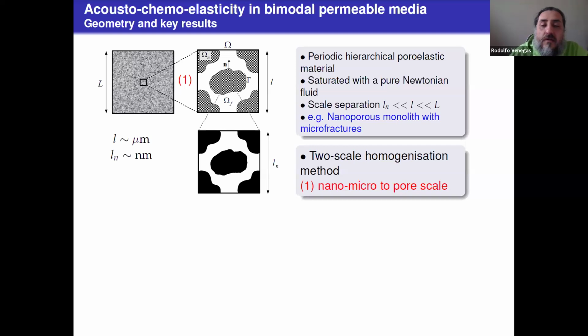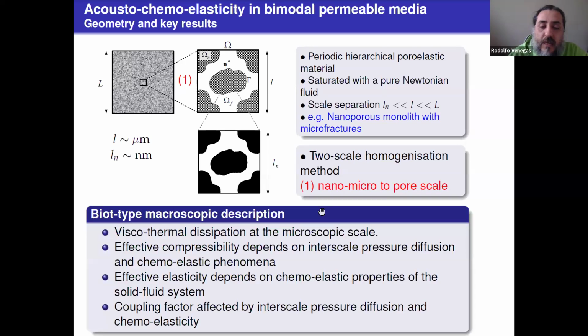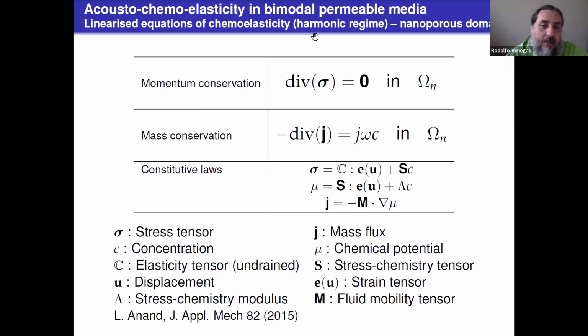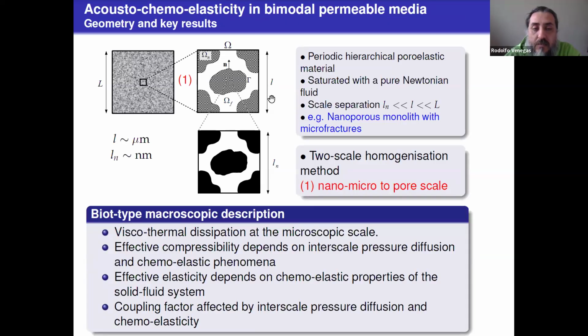So what's the other thing now? If we include fluids, things become a little bit more difficult because we have to account for effects of chemoelasticity. Chemoelasticity in the sense that we couple elasticity with diffusion. And we treat this in terms of chemical potential that has two contributions, one coming from, let's say, elasticity and the other one coming from concentration. We start with this system and we couple it with the Navier-Stokes system in this pore, and this system here is formulated in this part.